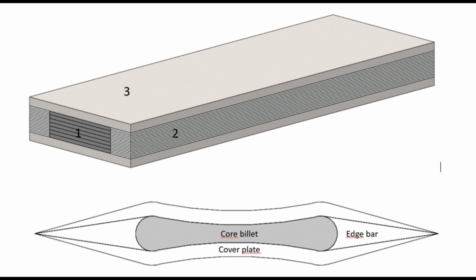One core billet, which was then flanked by 2 bars of edge steel, which is then fully encased by 2 cover panels. And because these cover panels reach all the way to the extremity of the cutting edge, it gives the appearance that the entire sword is made of a monosteel, but in fact this is certainly not the case.